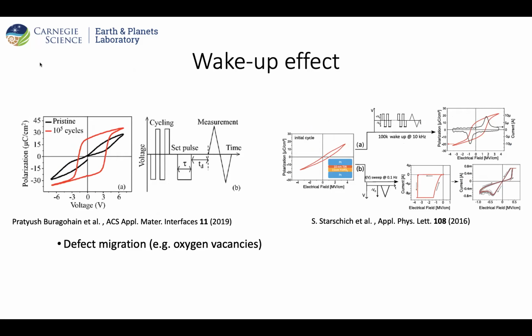Additionally, there's such a thing called the wake-up effect in Hafnia, where a Hafnia sample needs to be, let's say, given a wake-up call first. So you need to go through some cycling of electric field to bring the polarization to a larger value, the remnant polarization shown here. This wake-up effect usually is attributed to defect migration, which means we'd like to reduce this cycling so that we do not get a premature fatigue on our material. So the story I'd like to tell with this presentation is that of a stabilization with electric field and strain.